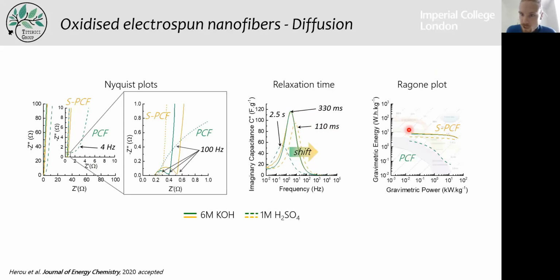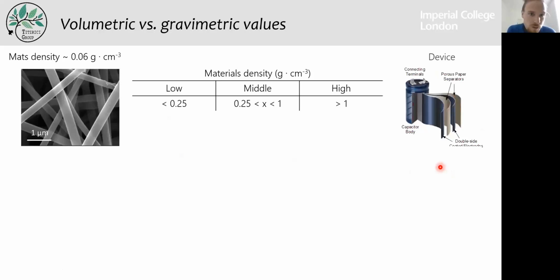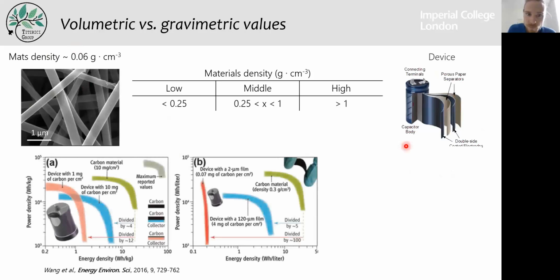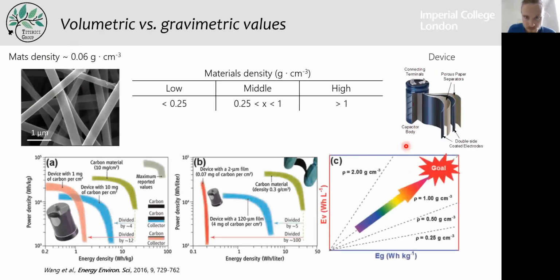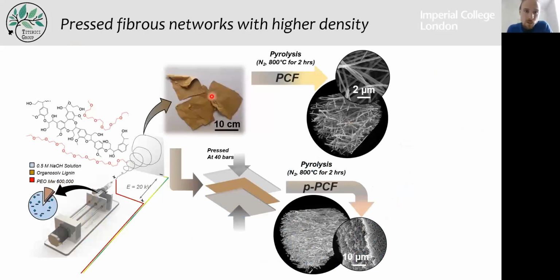And that is the energy density for all of these carbon fibers. It shows you that it's much higher than typical supercapacitors already on the market. So just very fast, as I'm lacking a bit of time, we try to increase the density of the mats because the problem of these mats is that they have really low density. And basically, we tried pressing these mats using 40 bars into much more compressed systems.